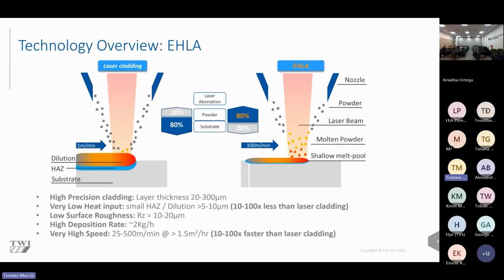So, a technology overview of EHLA versus laser cladding. Laser cladding is the traditional technology on the left-hand side. You're getting a good amount of melting and heat affected zone within the substrate. But what that does is bring the iron that might be in the substrate through the clad, and you will therefore have to put more layers on to get rid of that dilution of iron in the substrate through to the deposit.